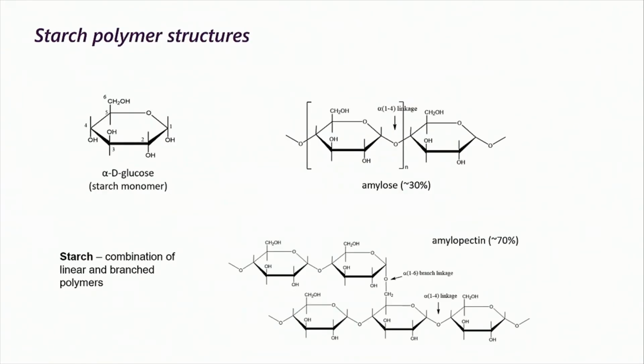There's a bit of a background on the chemical structure of starch. It's made up of alpha D glucose units, which you can see on the top right there, my right, your left. And it's made up of two polymer types, I suppose. The amylose is generally a linear polymer with molecular weight, say, up to about 1 million. It does actually have some long branches, very rarely along the chain, but it's generally regarded as linear. And then amylopectin, and it's a very large polymer. It has the branches, and it can have well above 1 million, tens of millions, and even above that in some cases.